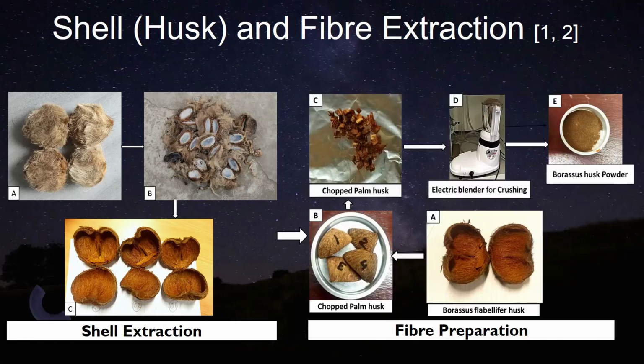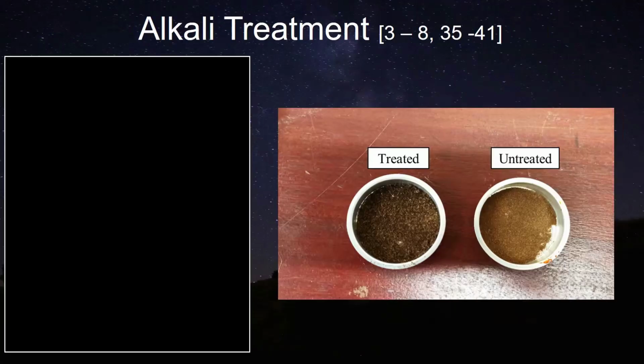Now, what I did, because the fiber is non-uniform in diameter, I crushed this to a powder so that we can use it. And you can see that in the image. Then, after the powder, because we know those biofibers are covered with pectin, hemicellulose, and wax, I need to take it out. And this is the treatment we do, alkali treatment. A lot of chemical treatments can be done, but for my research, I have done the alkali treatment.